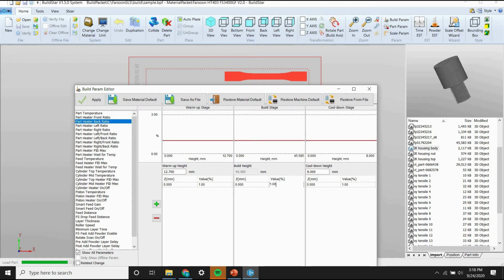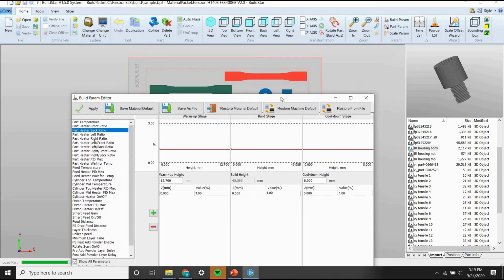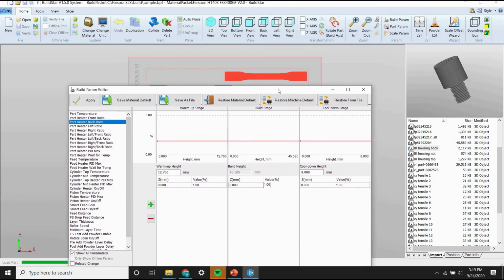If maybe you overshoot, and you start to see a melt pool, usually where the geometry of the part melts before the sintering process begins, then you can go back and decrease that percentage. But usually you change it 0.25% at a time. It's a good value to see where you're at.